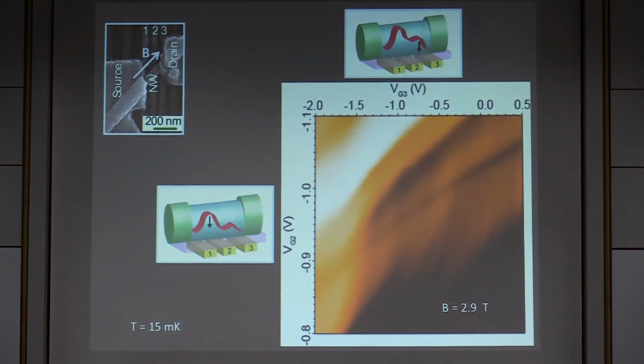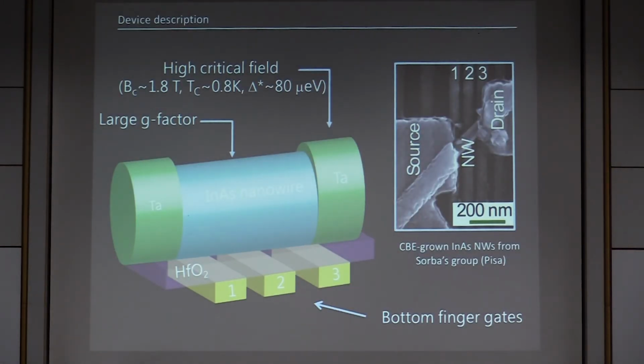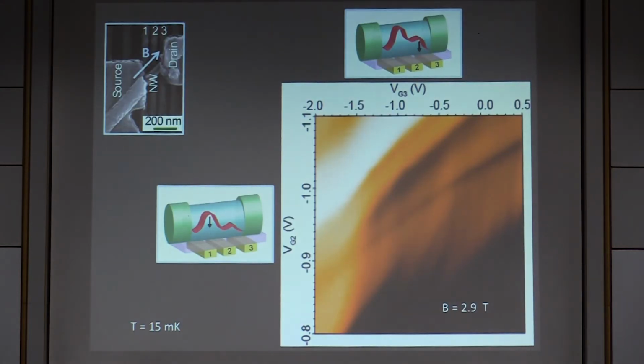Excuse me? Yes? The g-factor was large. How large in figures? Well, in this material, it was not super large. This is indium arsenide. It's around 11, something like that. Still, it is large enough to split the states, as compared to killing the superconductivity in the leads. So we can induce an important Zeeman effect. That's the key of the experiment I'm going to tell you.